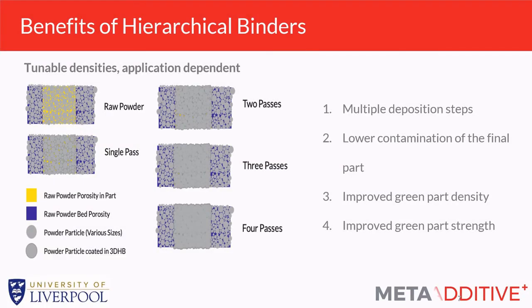Some other benefits here is the fact that we're infiltrating and binding simultaneously means we could do a multiple deposition step. So we could print more binder, more infiltrate, and we could tune the densities that we need depending on what application we're using. We also find that we get a much lower contamination of the final component, and that's because we're not using sacrificial binders, so we're not having to heat treat the binder out, which often leaves carbon residue. So the contamination of the final part is much lower.